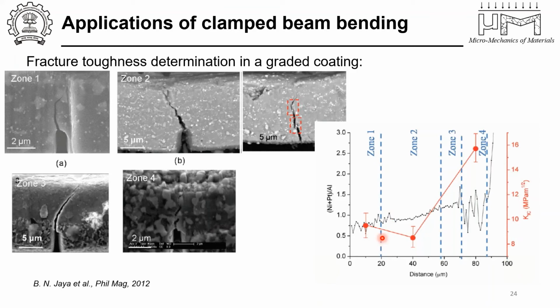So this is something we could record, and we could say where the coating would be the most vulnerable. Of course, under actual service loading conditions, it would be either at the substrate coating interface or right at the surface between the bond coat and the free surface. But the fracture toughness happens to be lower at the free surface end, whereas it's much higher at the interface between the substrate and the coating. So there are some predictions that you can make and put into models and look at what happens to crack growth in these kinds of coatings.